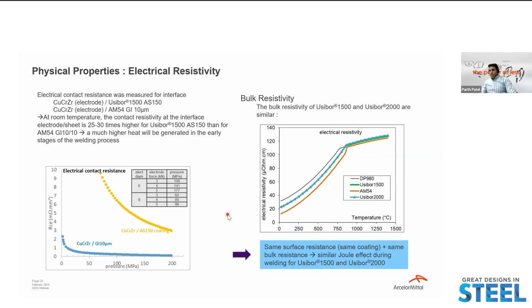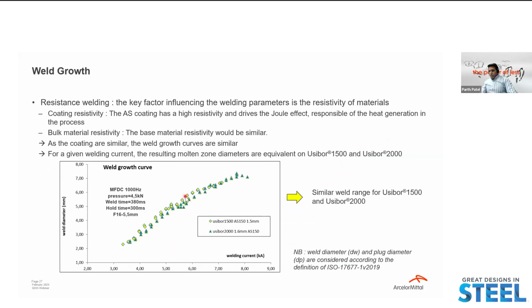But there are many parameters you have to take care of for welding, not just resistivity. Moving on to weld growth - if you have similar resistivity for coating, your parameters should be very similar. So if you're doing homogeneous welding, Usibor 1500 to Usibor 1500 or Usibor 2000 to Usibor 2000, your welding parameters should be very similar to each other according to the weld diameter you want. So your coating really matters - if your coating's transformation is very similar for each material, you'll have very similar process parameters. There's a myth that 1500 and 2000 are going to be very different, but for homogeneous welding, it's very similar. For heterogeneous welding, it could be different because you're adding new surfaces with different coatings.